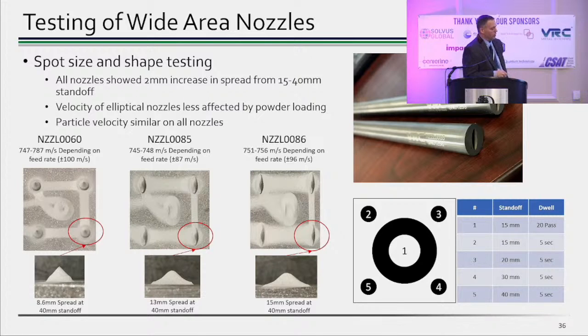So now, if we want to look at what the deposition looks like, you can see these are plates that were made with 4 spots and a circle in the middle just to look at the different paths and what the mounds in the corners look like. And you can see that with the circular nozzle, as you'd expect, you get a little Hershey kiss, right? And then when you go to these elongated nozzles, you get this wide spread of material going all the way from 8.6 millimeter spread on the circular up to 15 on the widest spread. So now that's going to allow you to change your overlap, your step.